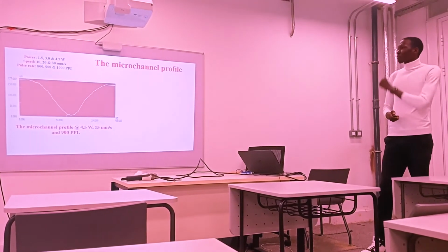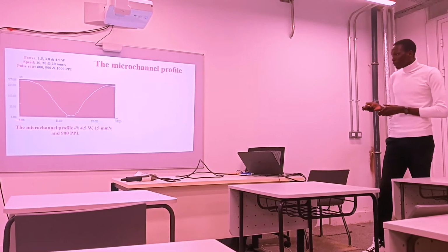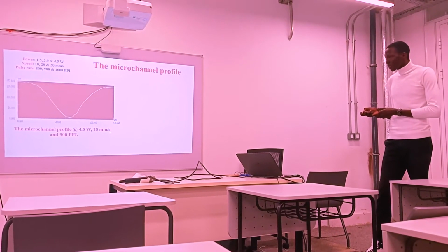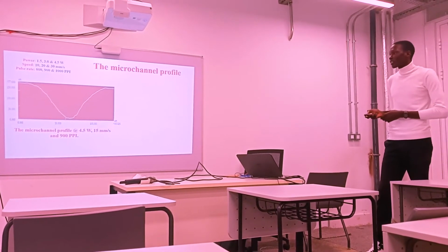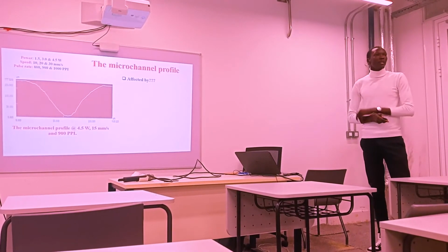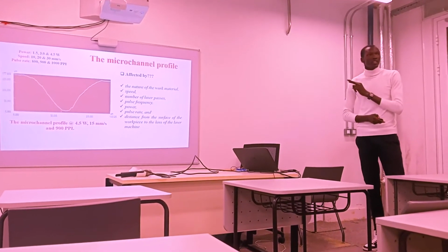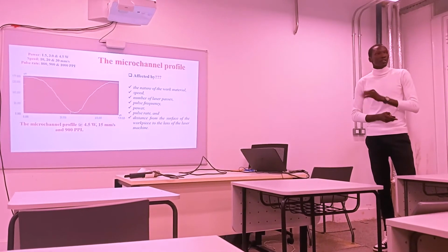Now, this is a microchannel profile that we got at 4.5 watts, 15 millimeters per second, and 900 pulses per inch. The microchannel profile is affected by many factors, like the nature of the work material, the speed of the laser beam, the number of the laser pulses, the pulse frequency, power, and many others.